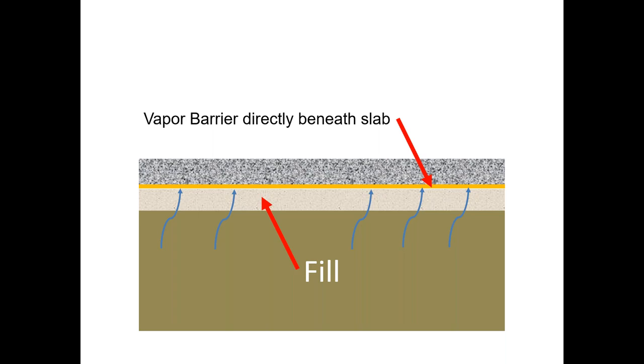But what I would say is that when we start talking about actually putting moisture sensitive flooring down on a slab, then having that vapor barrier there is critical. Point number two is that the challenge of urgency to occupy the slab drives a curing compound or membrane, et cetera, at the surface, even if trying to control cracking, which traps the moisture in the slab. So now you have a vapor barrier on the bottom of the slab and a coating, even if breathable, on the surface. Water has a harder time exiting the slab during curing.